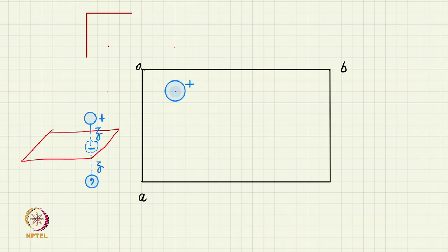If I project these two, they will project in the same location. So, in the projection, one has to represent 2 points, one above at plus z and another below at minus z, and the two are of different handedness. So, the standard notation used for this is to divide the circle into half, and then show the change in handedness by a comma in half of the circle.